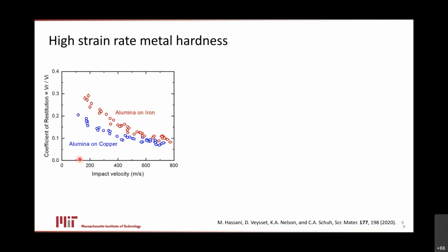And so this is sort of a measure of the bounce, if you will. So we're talking about having bouncier things here, and then as we go to high velocities, we get less and less bounce. And that's a signature that we're doing more and more plastic work to that copper substrate. So this is a very quantitative test. In fact, you can see experimental error bars on these points, but they're very, very small. So we actually have a very high fidelity measurement of the plastic work that we've done to the substrate.